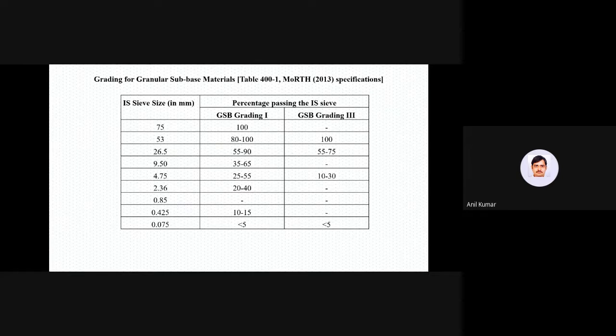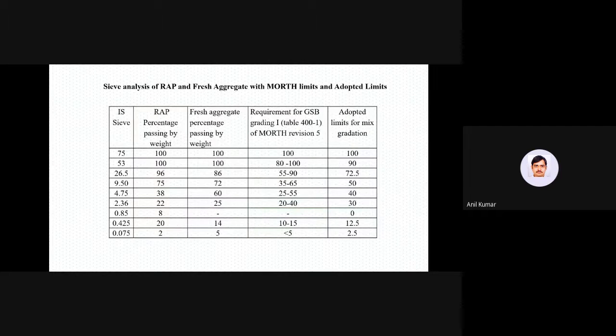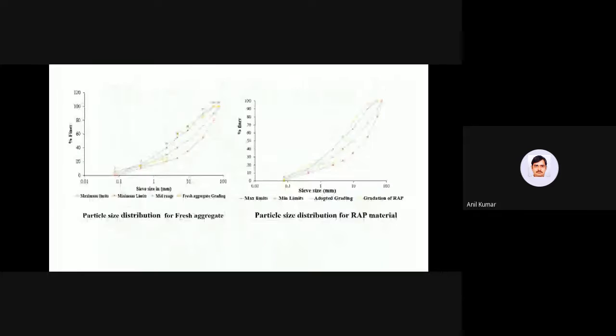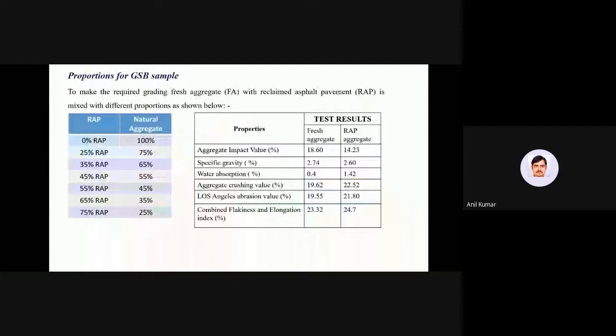This is the general grading of grading 1 and grading 3 of the subbase layer, that is prescribed by MoRTH. And here is the gradation of the aggregate which we have collected. This is the gradation graph of RAP and fresh aggregates, which shows that both the materials cannot be used alone for the construction operations, because they do not satisfy the MoRTH limitations. The proportion of GSB sample.